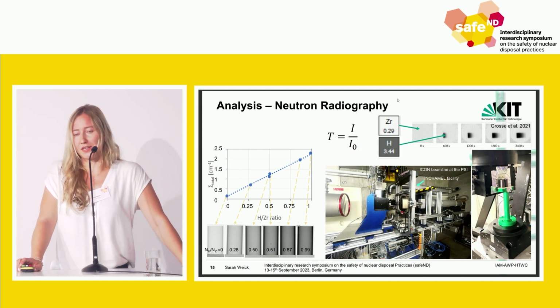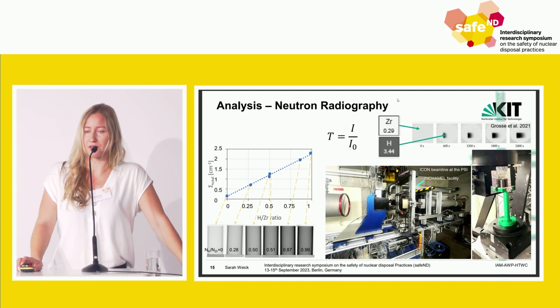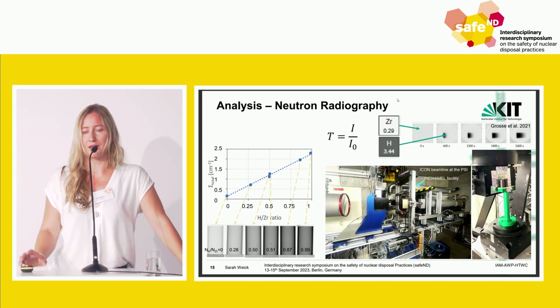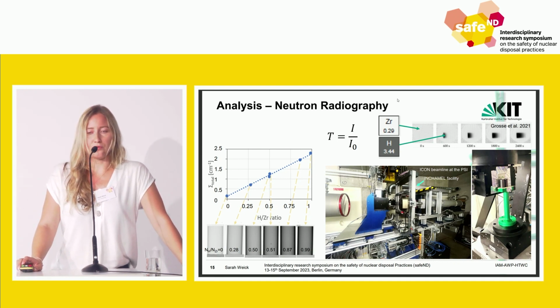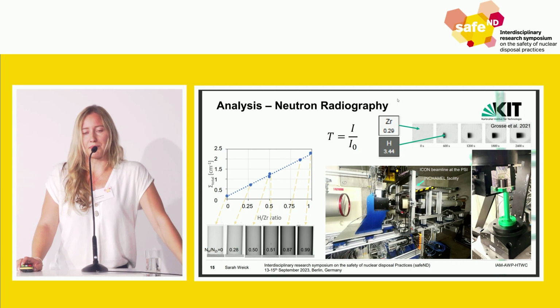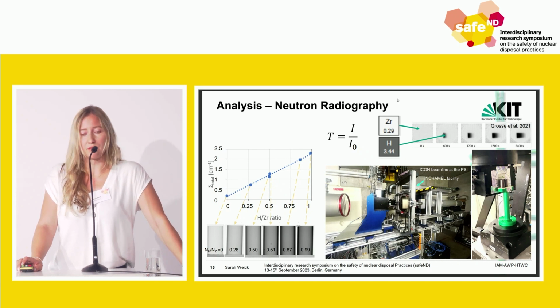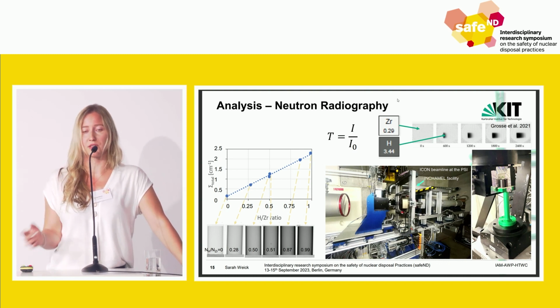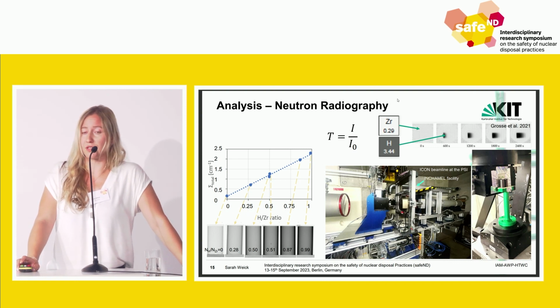On the other hand, hydrogen appears as dark contrast, as you can see on the right upper hand. Therefore, we need some calibration samples where we know exactly the hydrogen content, and with these calibration samples and the curve that you see on the left, we can calculate the concentrations of hydrogen in any of our other samples.